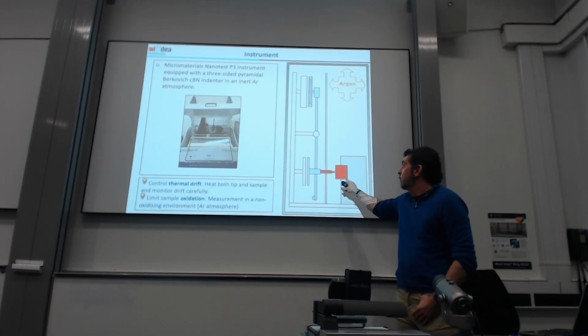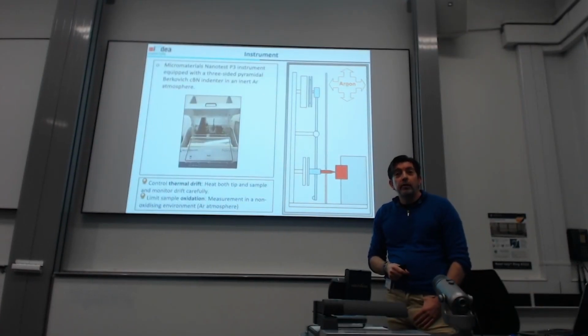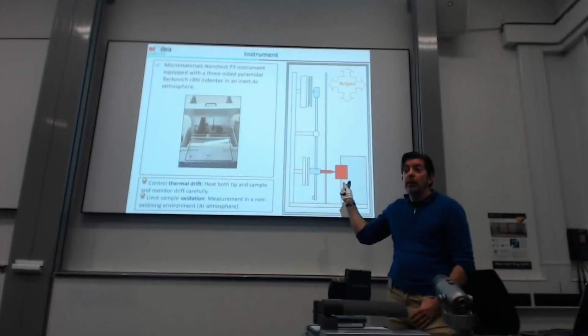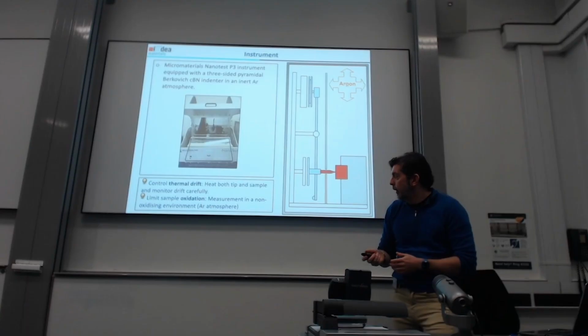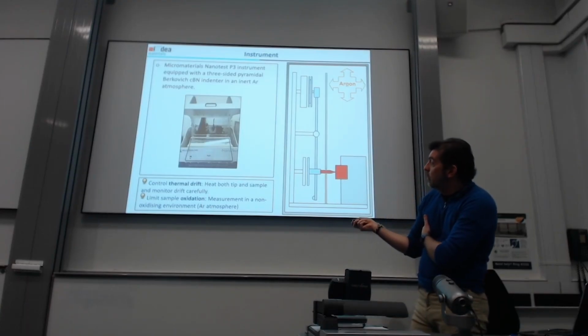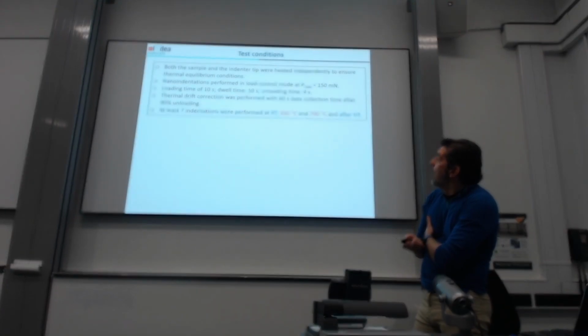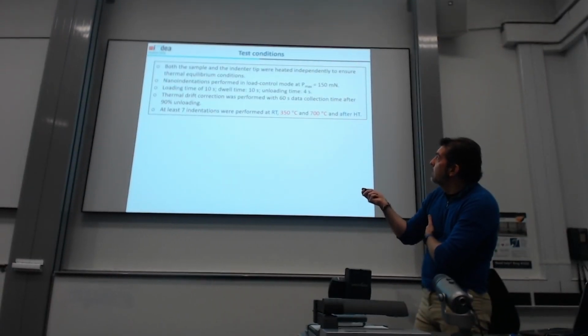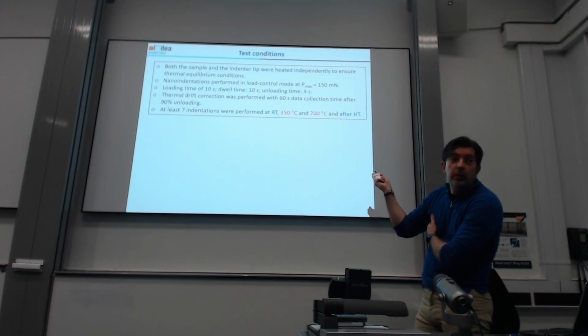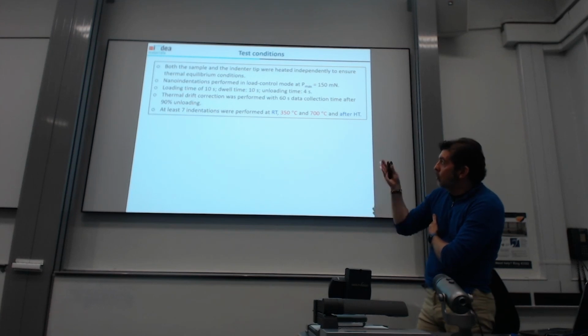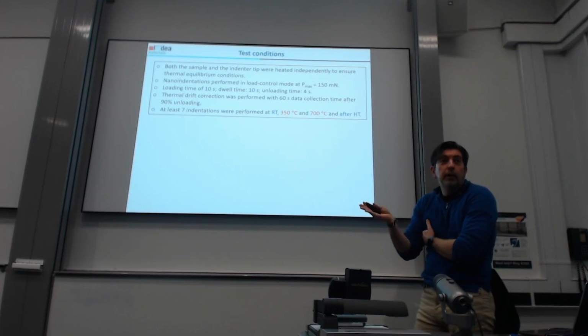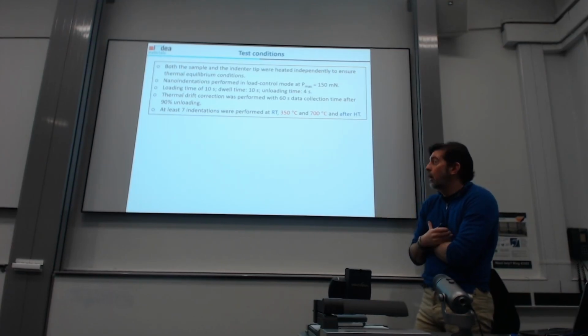As we know, it's important to control the thermal drift, and do this in an argon atmosphere at 700 degrees. We want to limit the oxidation, and we want to limit the drift. And these are some experimental parameters. I used a maximum load of 150 millinewtons, 10 seconds loading time, 10 seconds dwell time, 4 seconds unloading, and the thermal drift correction after 90% of unloading, a typical strategy used for high temperature.